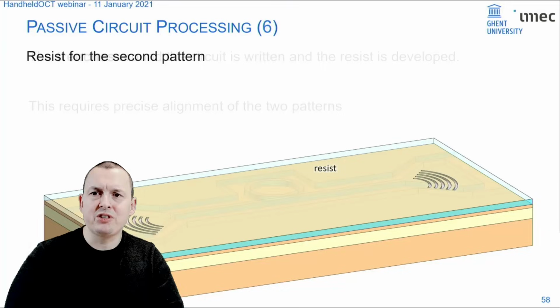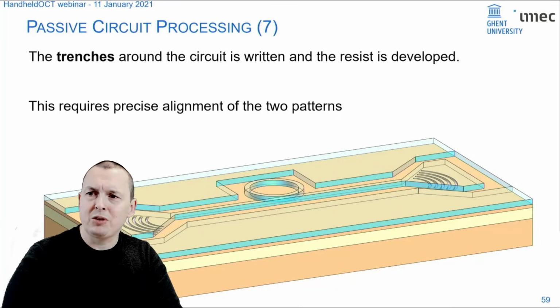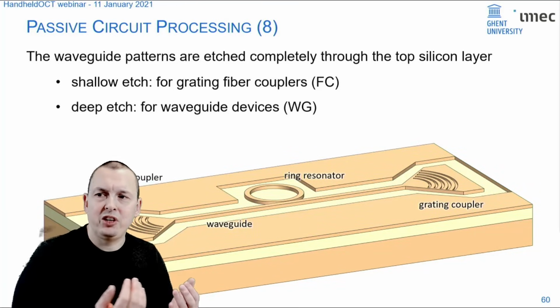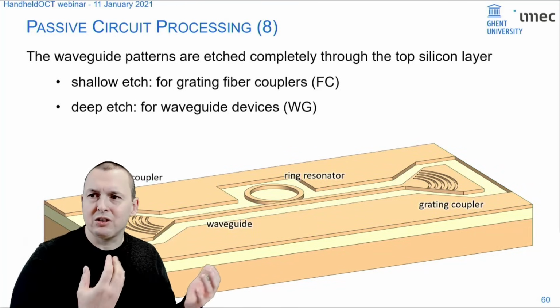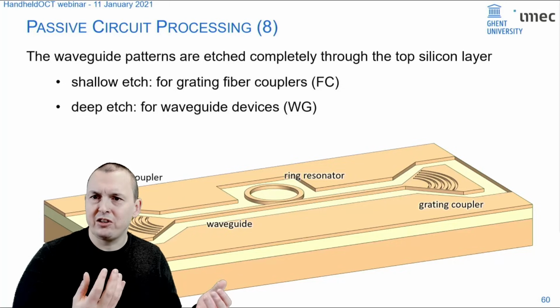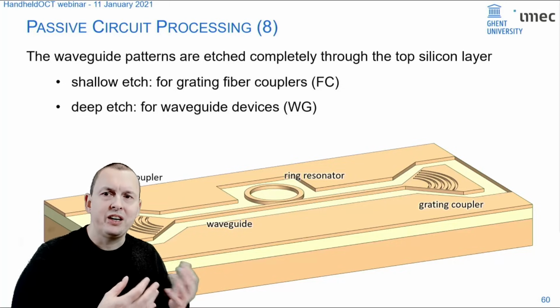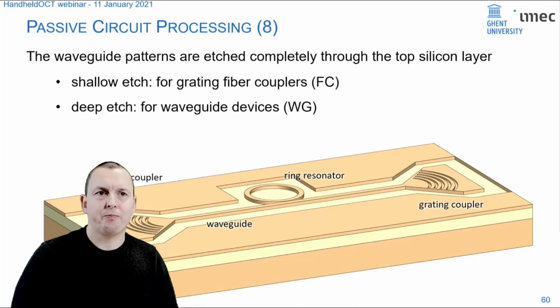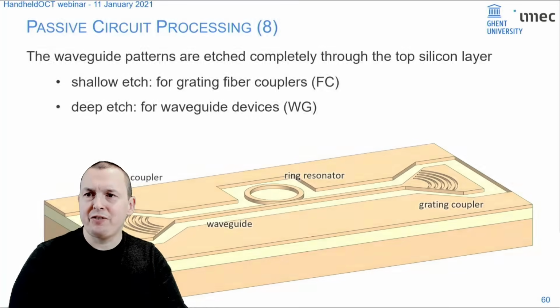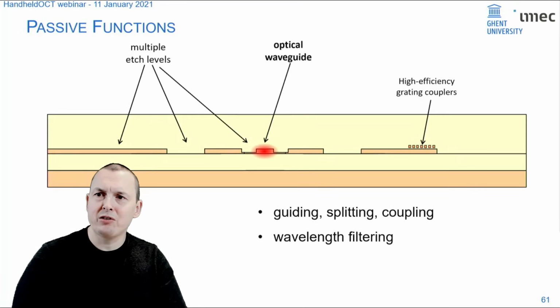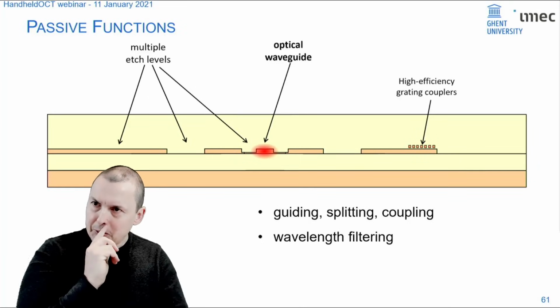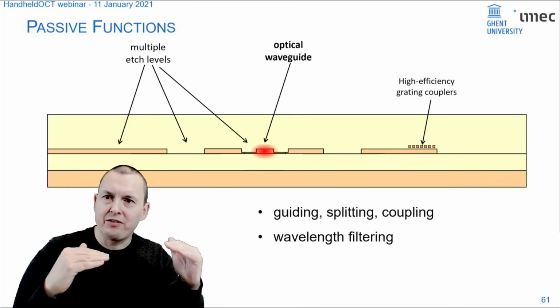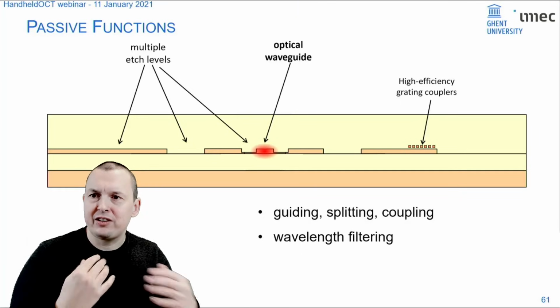And then you can repeat these steps again. You can deposit resist again. Now you pattern some other patterns. In this case, it would be trenches that define the waveguides. And then you etch these trenches away. And what you see now is a circuit that consists of 2 grating couplers to interface to a fiber and a ring resonator connected with waveguides. Now these passive functions essentially just require cross sections that look a bit like this. So with multiple etch levels, you can define optical waveguides, you can define gratings, etc.